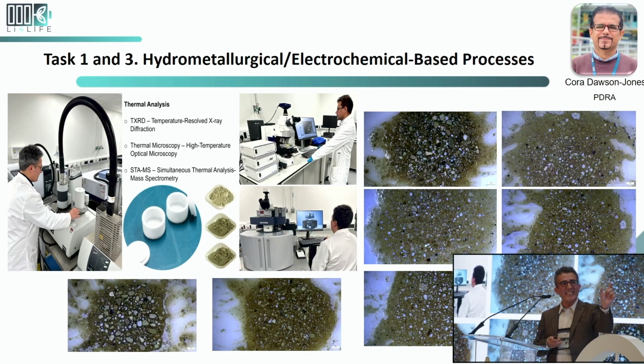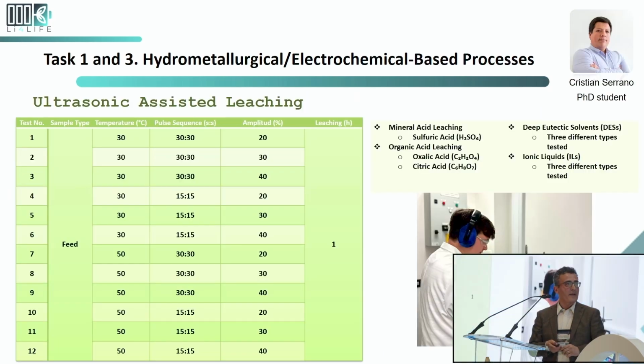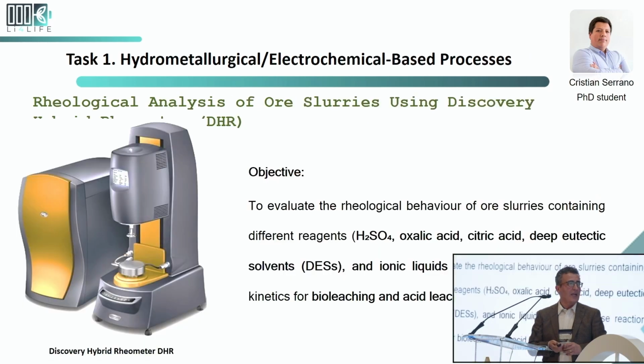These are thin sections, but not normal thin sections, because we expose our thin sections to 600 degrees. So we have to use a different binder to produce these thin sections. Then we can use our thermal analysis. We also use some other techniques, ultrasonic assisted leaching. In most cases, specifically for organic acid, we have seen very interesting results.